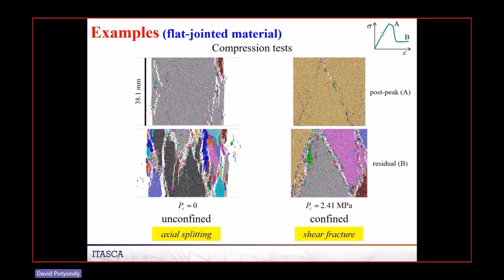So the stress strain curve looks like this, has this residual value. So at the peak here, just past the peak, this is what the system looks like. It's just beginning to form a shear band. If you keep applying more axial strain, it drops down and comes to a residual value, and that's because these shear bands are now fully formed. And once they're fully formed, we have a kinematic mechanism where we have these fractures with friction on them effectively. And so that's now this residual system. And so that's why this thing goes down and then reaches this residual value.